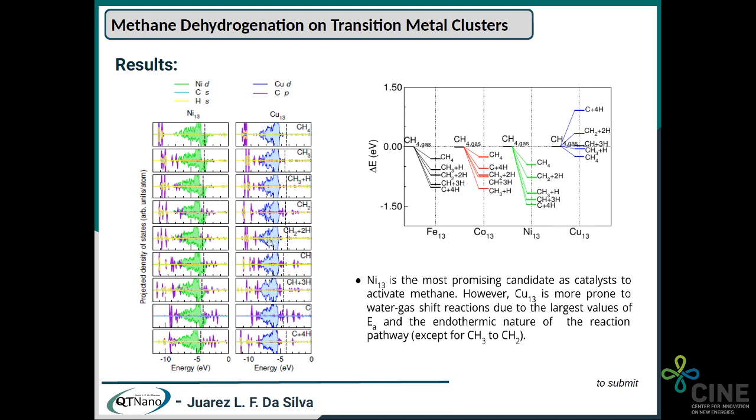One of the reasons is that copper has full occupation of the d states, and we also have a shift of these states towards the negative direction, which does not favor the hybridization with the sp states from carbon. And when we include the hydrogen, we can see that the dissociation energy increases, and we maximize the effect of this hybridization, now with participation of the s states from hydrogen.